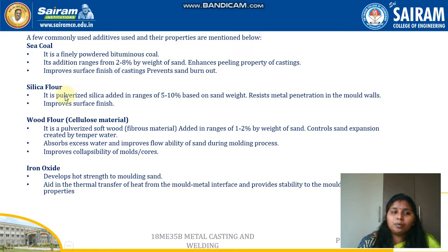The next additive used is silica flour. It is pulverized silica added in ranges of 5 to 10% based on sand weight. It resists metal penetration into mold walls. It improves the surface finish.